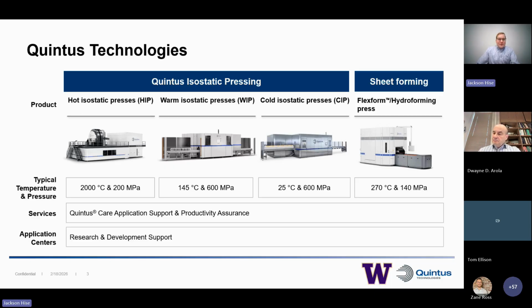So just a background on Quintus Technologies. Quintus Technologies' work revolves around isostatic pressing. The only real difference as an equipment manufacturer is what medium we're applying to the vessel in order to pressurize our parts. So of course, we're going to be talking about hot isostatic pressing here in this presentation. We're using argon often as the medium, and we're applying a temperature up to 2000 degrees C on our material with 200 megapascal maximum.